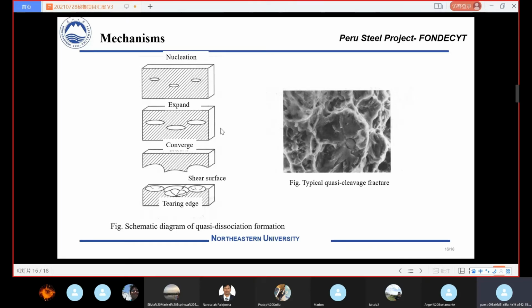And if the crack initiates, then it will propagate outwards. The second phase plays an important role in the propagation process. Of course, it also plays an important role in the crack initiation process. So we should take care of the second phase, and we should notice its size, shape, distribution, and volume fraction.